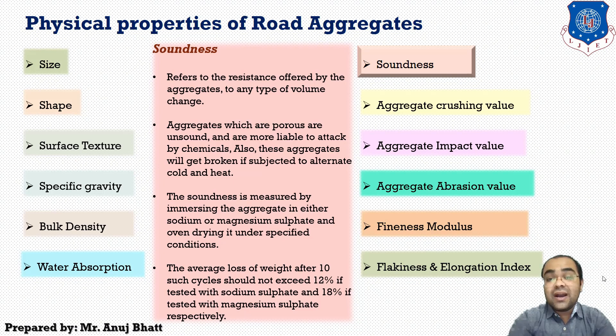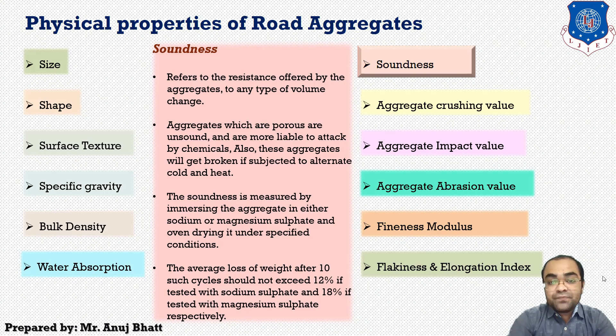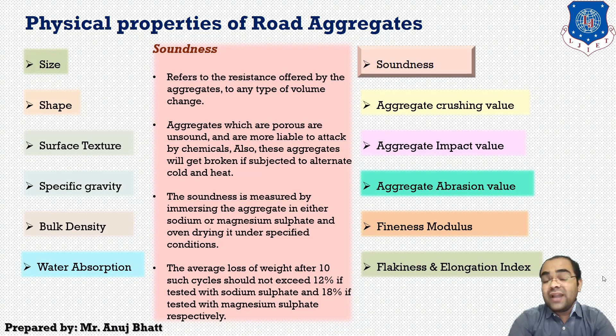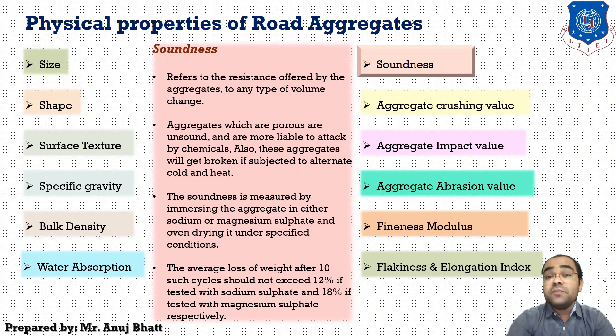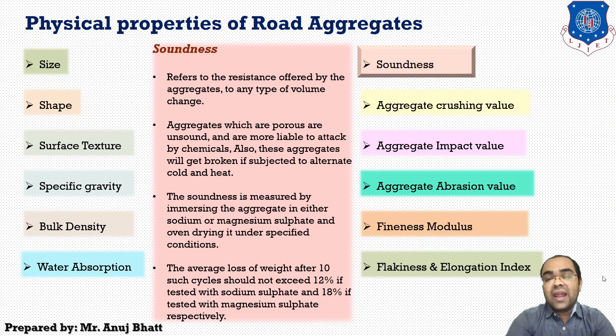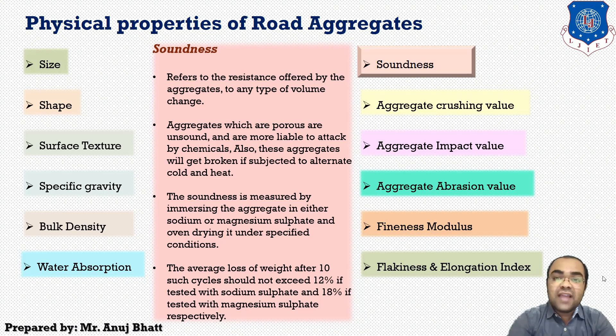Aggregates which are porous are unsound and are more liable to attack by chemicals. These aggregates will also break if subjected to alternate cold and heat, so variation in weather also affects the property of aggregates. Soundness is measured by immersing the aggregate in either sodium or magnesium sulfate and oven drying it under specified conditions. The average loss after 10 cycles of drying should not exceed 12% if tested with sodium sulfate.